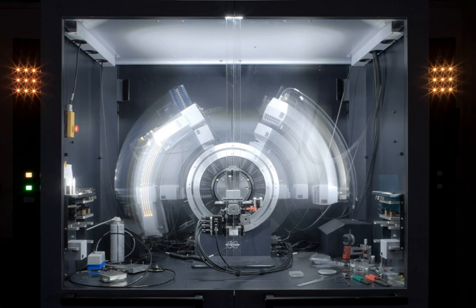It is customary to rock the crystal slightly by 0.5 to 2 degrees to catch a broader region of reciprocal space. Multiple data sets may be necessary for certain phasing methods. For example, MAD phasing requires that the scattering be recorded at least 3 and usually 4, for redundancy, wavelengths of the incoming X-ray radiation. A single crystal may degrade too much during the collection of one data set, owing to radiation damage. In such cases, data sets on multiple crystals must be taken.